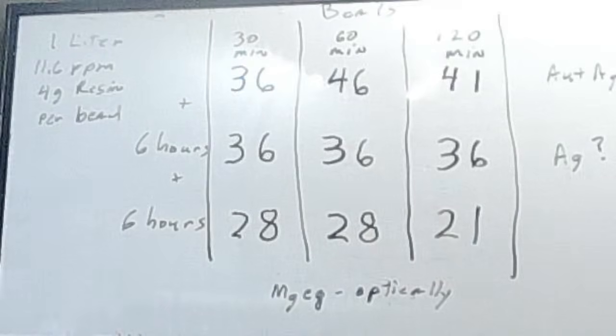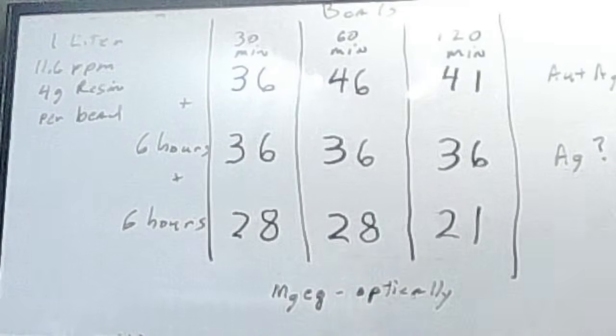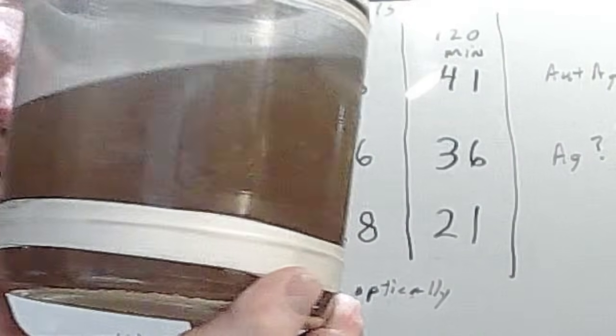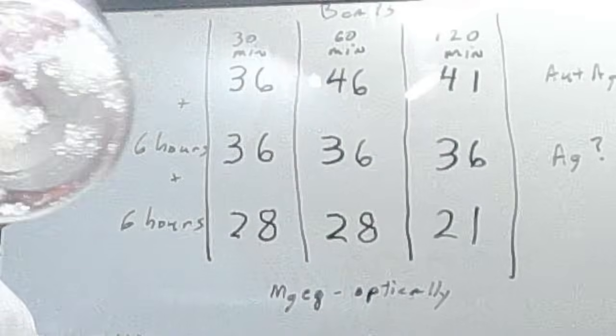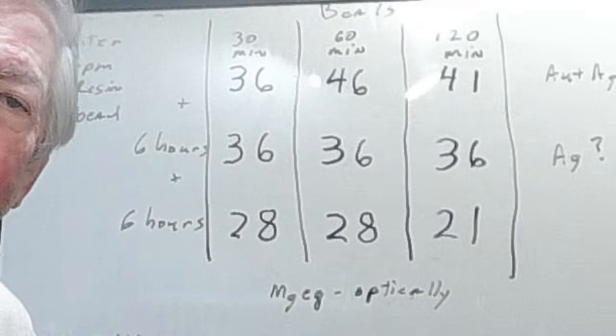Well, we don't do electrolysis on quantities this small because the quantity is too small. We electrolytically extract gold from resin all the time when we have a full load of resin and plenty of gold in it. But this is just a test. Okay. We start out with this amount of solution here. Into that amount of solution, we put that much resin, 4 grams.